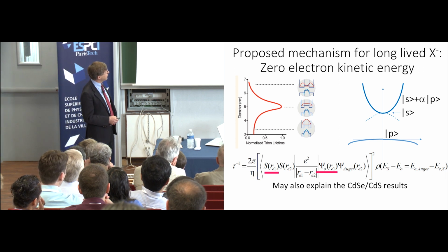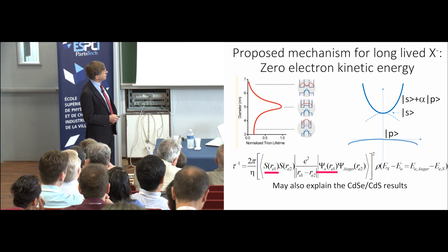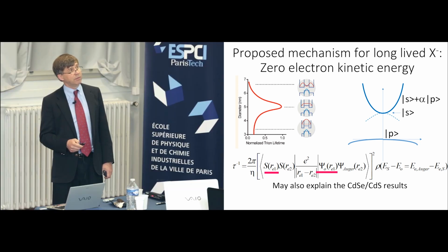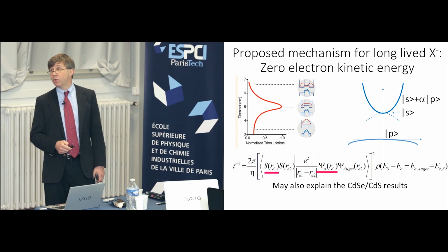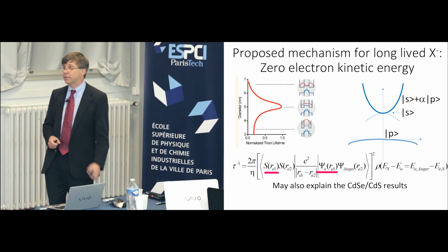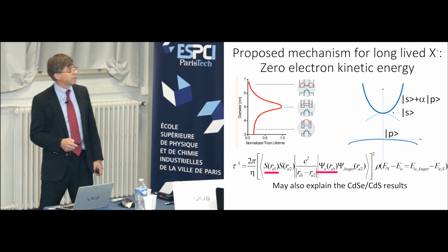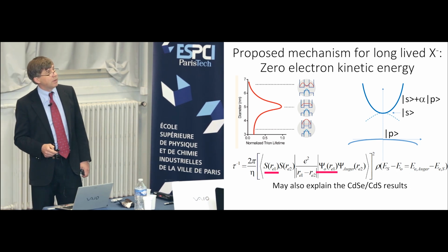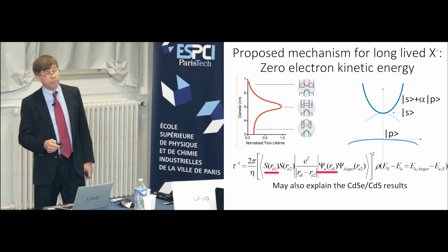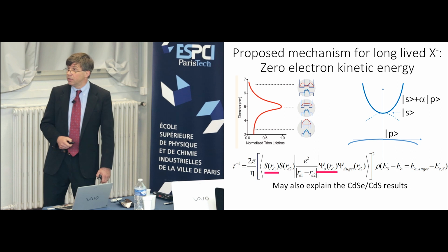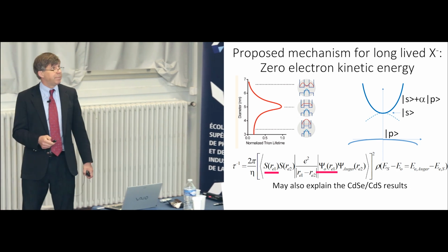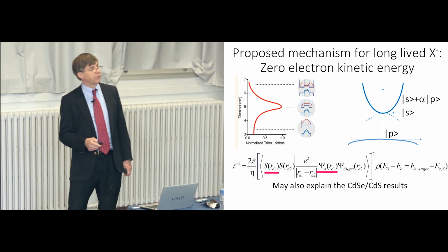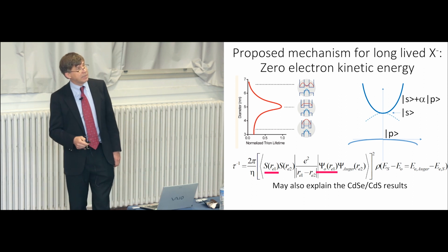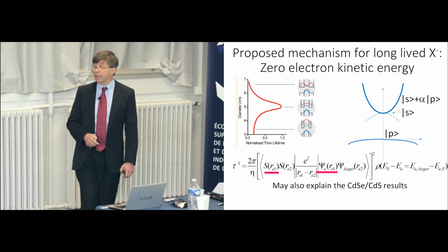And what we realized was that if we have zero kinetic energy, then we have a pure S-like Bloch function of the electron and a pure P-like Bloch function of the holes. There's actually zero spatial overlap. They are at separate spatial positions. So that should be identically zero. But as you move away in the conduction band, as you pick up kinetic energy, either with the real wave vector or the imaginary wave vector, you start mixing in the P atomic orbital or Bloch function with the S one. And so now you can imagine that you're going to get some spatial overlap.